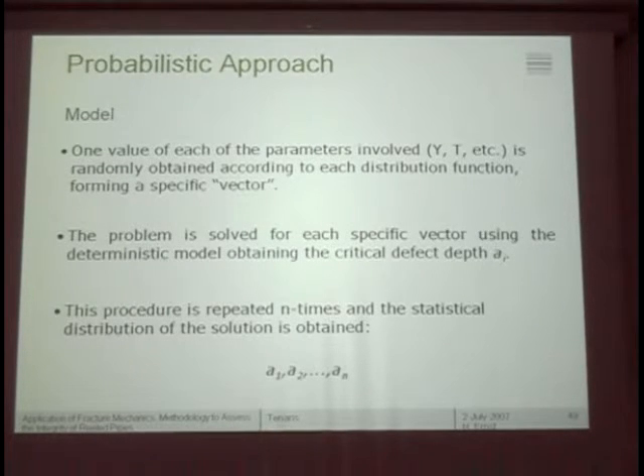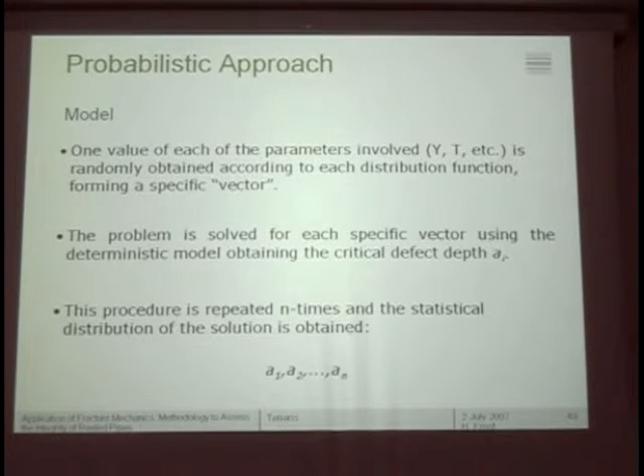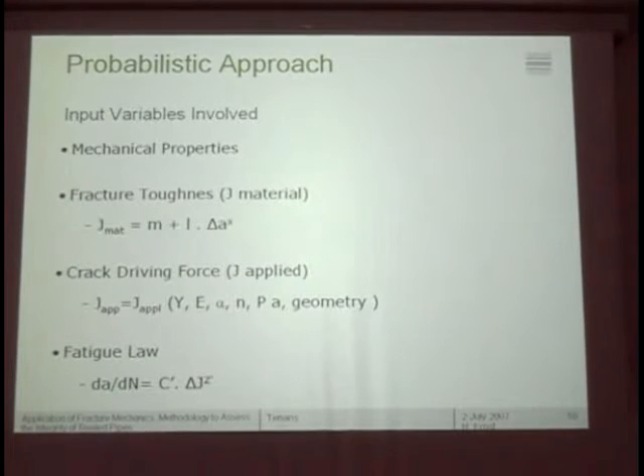Basically what we do is pretty obvious, we include there, as I said, all the statistics. We sort of throw the dice, if you like to say, and with that we come up with a vector, and the problem is solved for each specific vector using a deterministic model. Then you repeat that 10,000 times, or however many cases you have the patience to wait, and you solve the problem this number of times.